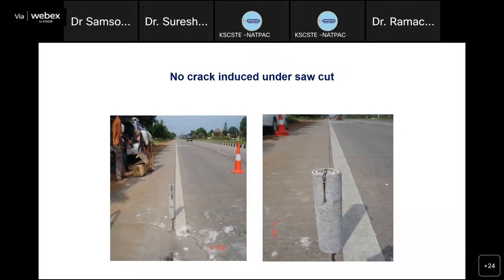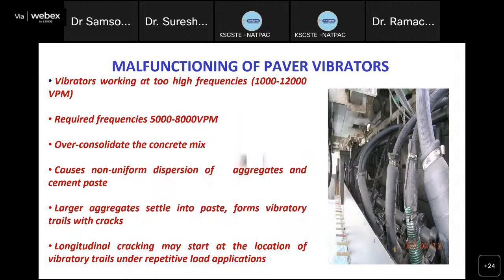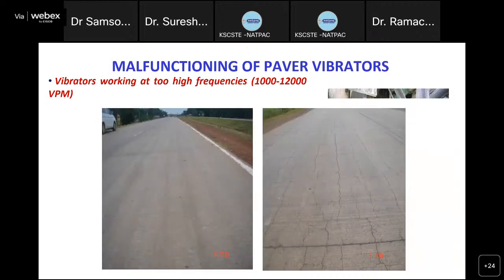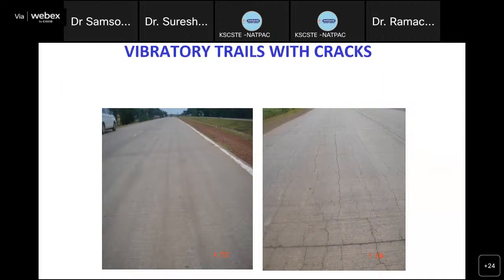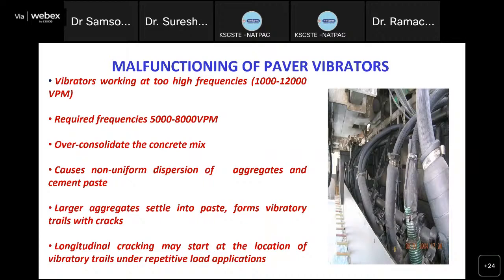Sometimes we may have cracks something like this. These are not longitudinal cracks. These are vibratory trails, small cracks which occur at the surface. These are not the longitudinal cracks which I showed earlier. These are vibratory cracks. This happens because of the vibrators that we use in the slip form paver or in the fixed form paver, if we have mechanical vibrators. The frequency with which the vibrators operate determines or causes this kind of cracks.